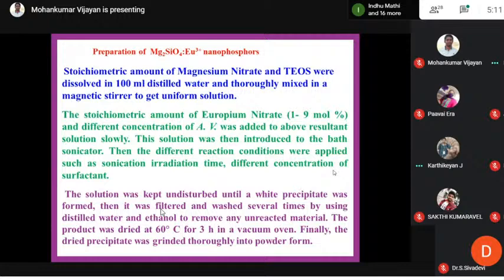This solution was then introduced to the sonicator, that is a bath sonicator. Then the different reaction conditions were applied, such as varied sonication time and irradiation time. Different concentrations we have used. The solution was kept undisturbed until white precipitation was formed. Then it was filtered and washed several times using distilled water and ethanol to remove the unreacted material.